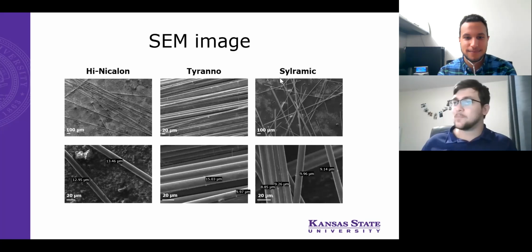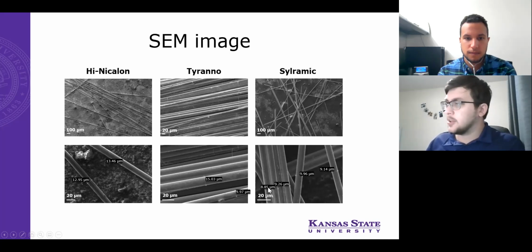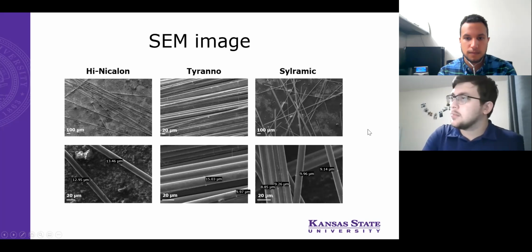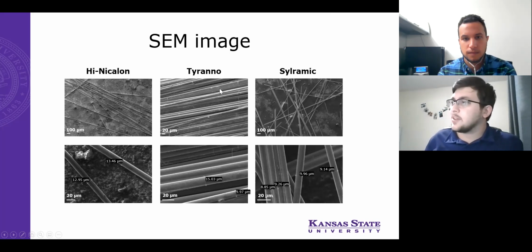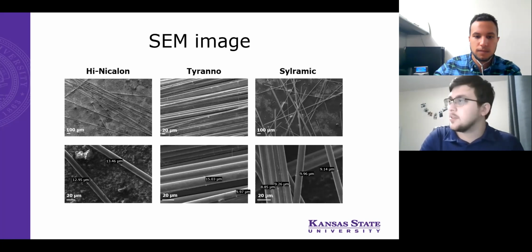So the Hi-Nicalon had a more consistent diameter at about 13 microns across its samples, and you can see that again here, that they're pretty consistent. Whereas the Tyranno actually had some inconsistent diameters throughout. So this one was at about 10 microns, this was about 15. So the diameter was not necessarily the same in all of the filaments throughout the tow. And then the Sylramic, again, a little more consistent, with around 9 or 10 microns for each filament. Oh, and also you can note the Tyranno looks to have some sort of coating on it there and here, which will likely affect the properties that we examine.